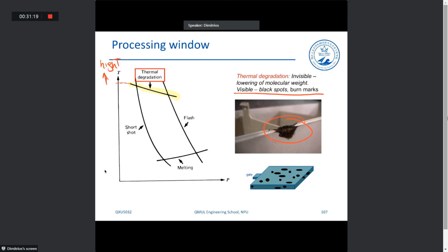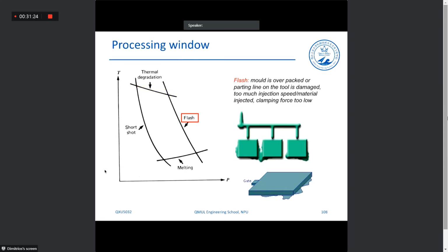Now, flash is another problem with injection molding, where in this case the mold is overpacked, or we have too much speed or material injected in there. And because we have too much material injected in there, the material looks like that, okay? In the simplest cases, we can simply cut these materials off. In an academic laboratory, I've done it several times myself. I've overfilled our mold, and by overfilling the mold, you end up having these materials. And then in an academic environment, you just cut them with a scissor or whatever. But in an industrial environment, you cannot deal with these on a one-by-one case, because you're producing so much material. So you don't want that. So flash takes place when the mold is overpacked, or we have too much injection speed or material.